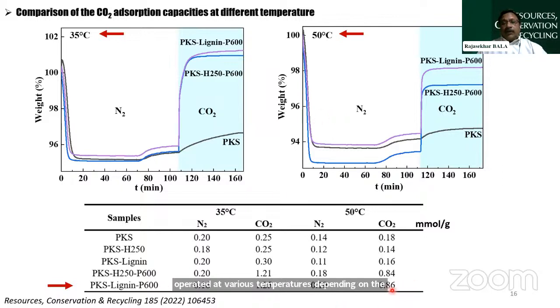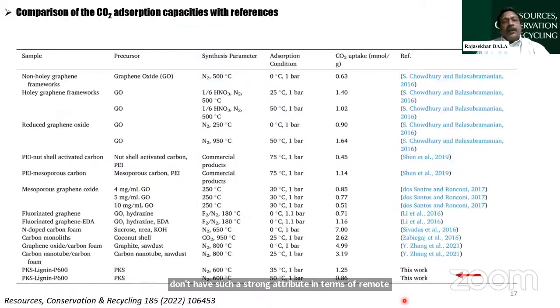And what's even more important for us is to realize that the adsorption capacity is much larger for our carbon foam as compared to all other products that we could get from the same feedstock, that is the PKS, the biomass feedstock. They don't have such a strong attribute in terms of removal of CO2. Okay, so then we want to compare our material with all other materials that are potentially available for industries to use. This kind of comparative evaluation is very important for us to make an appropriate selection of the material. And you could see over here, once again, our carbon foam has superior properties at 2 different temperatures as compared to most other materials, I would say.